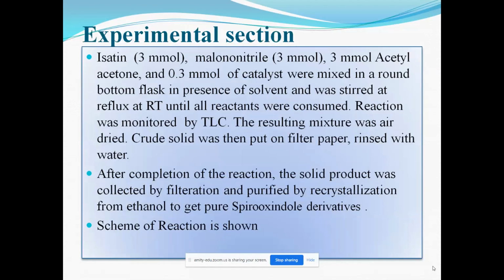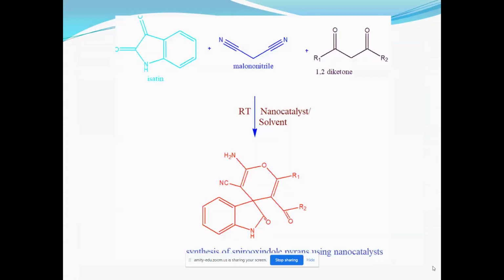In the experimental section, I have used isatin, malononitrile, and acetylacetone, which is a 1,3-diketone, in equimolar amounts and 0.3 millimole of catalyst in a round bottom flask, and stirred and refluxed at room temperature. The reaction progress was checked by TLC, and the crude product was then separated out and rinsed with water. This is the scheme of the reaction.